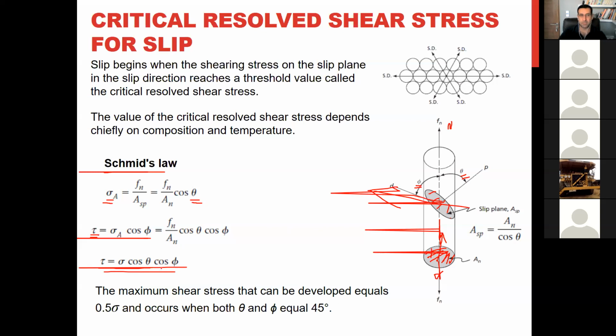And by these angles, you can easily calculate that when theta and phi are 45 degrees, we have the minimum applied stress needed for the resolved shear stress for a slip. It means when you're applying load, if your slip system is at this angle, you need minimum stress to move these planes together, and this is 45. So this is the reason why in that previous test, the slip plane, or basal plane, of magnesium had an angle of 45 degrees to the direction of the load.